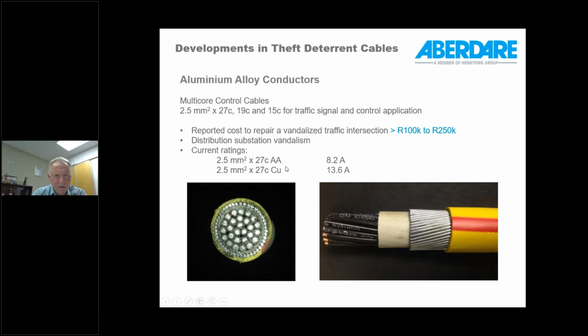Just as an illustration, a 27 core 2.5 aluminium alloy cable has a current rating of just over 8 amps, and the equivalent copper cable has a current rating of about 13.6 amps. So that's a significant difference. If one required this copper cable current rating, you would need to increase the size of your multi-core, which obviously can result in some problems with sizes and bending and so on, particularly when you get to the higher core count of some of these cables. But it is definitely a solution